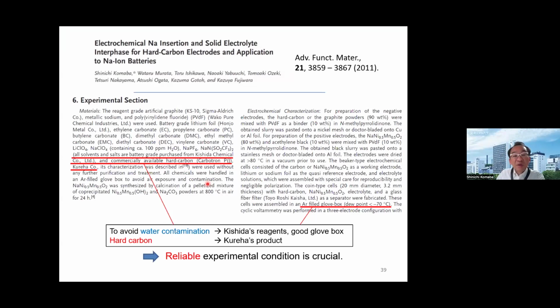So in our paper in 2011, we mentioned the important experimental conditions for electrolyte and hard carbon. I mean that water contamination into the electrolyte solution is very, very important. Then we carefully optimized them. Finally, the dew point must be quite low in the glove box. And also we should carefully choose the electrolyte quality.